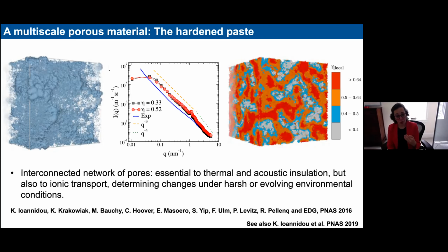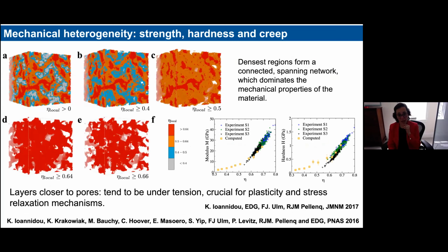But of course, you can do more with this type of simulation because you can compute the mechanical properties. For example, here we have computed the indentation modulus and the hardness by doing different types of computational mechanical tests. And we can superimpose our data with the data from nano-indentation experiments that our colleagues at MIT did. You can see that our higher densities overlap well with the experimental data, whereas we have a whole range of moduli values that correspond to lower density gels that are not actually mapped to the experiment.